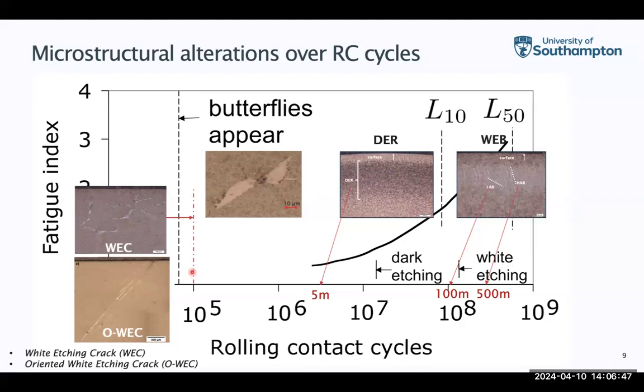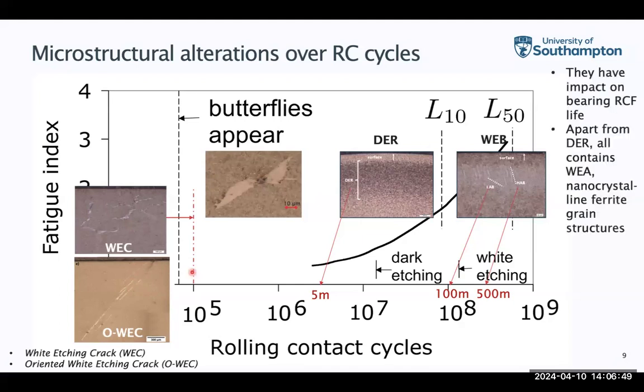So we have found all these different types of features, and they all have their own impact on the bearing rolling fatigue life. Some of them lead to early failures, like the white etching cracks and orientated white etching cracks. Some don't, like the butterfly, dark etching region, and white etching bands. Apart from the dark edging regions, which is also a microstructure alteration but doesn't have it, the others all have what we call white etching areas.